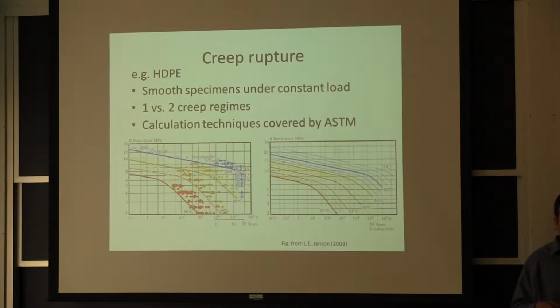At the same time, you do have a softer material, so if you were to have a brittle mode, you may not pick it up in your testing, but it will happen in the actual service because you're correcting for the flow of the material, but you're not capturing the effect of the hydrostatic pressure in terms of forming voids because you're just really reducing the load on your system.